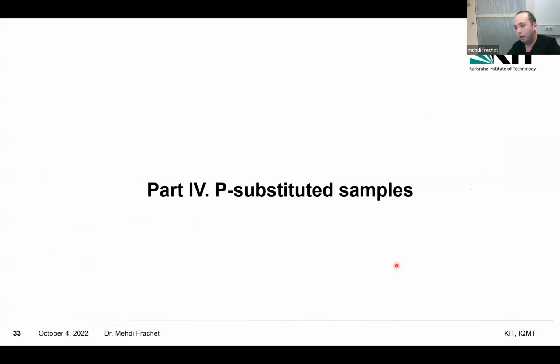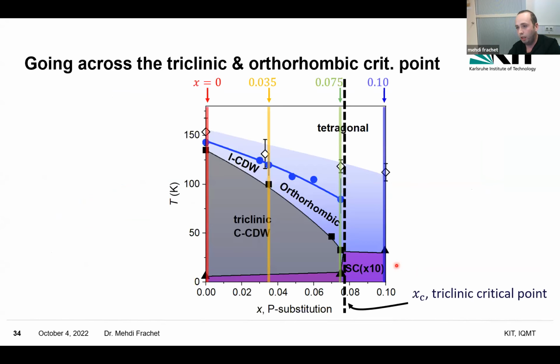Okay, so now let's go to the phosphorus substituted samples. So I already discussed this undoped compound, and I will show you now 3.5% of phosphorus doping, 7.5, and 10%. And for this last one, as you can see, there is no more orthorhombic structure or triclinic structure. Okay, so we are across the triclinic critical point, and there is a Tc of 3 Kelvin or something like that, a bit more than 3 Kelvin.